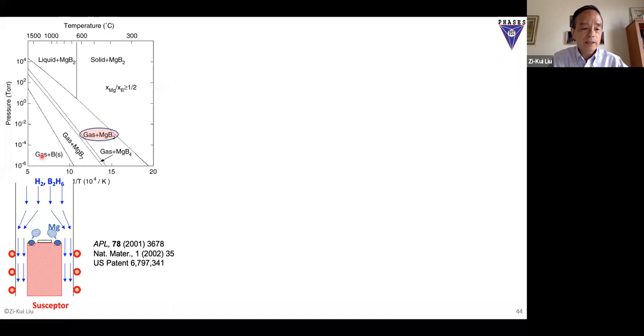So we worked together to develop a method called hybrid CVD, because CVD can give a very high vapor pressure. You put magnesium inside the chamber, and with the diborane gas, hydrogen comes in, then you form the film. We made a very nice film - 100% pure magnesium diboride without oxygen, since oxygen is expelled in the CVD process, and almost no defects in the making.